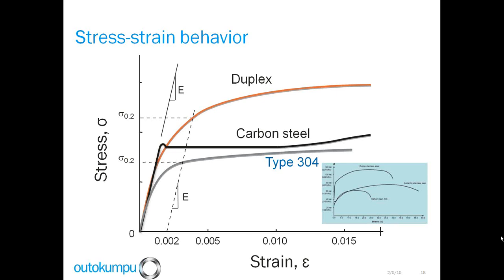If we now look at the plot of stress versus strain behavior and look at the 0.2% offset, it illustrates that duplex has higher yield strength than both carbon steel and 304 stainless steel. The yield strength of duplex is approximately twice that of 304 stainless steel.